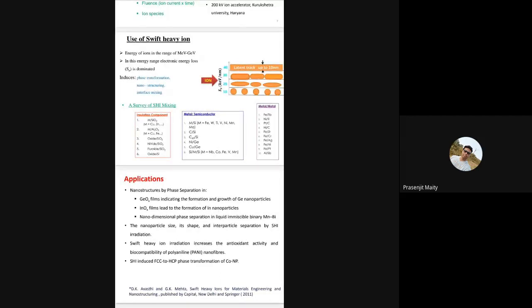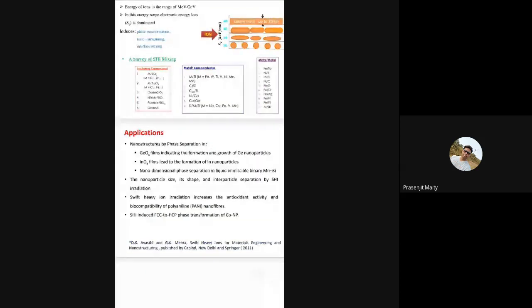Another important application in this context is nanostructures. People synthesize them by different methods, but ion beam irradiation also influences the nanostructure through phase separation, like germanium oxide film formation with nanoparticles. Indium oxide leads to the formation of nanoparticles. So there is a phase separation of a binary system, two binaries are there. By application of swift heavy ion irradiation, we can separate the nanoparticles of these two phases. The nanoparticle shape, size, and interparticle separation depend on the irradiated beam energy and different parameters.